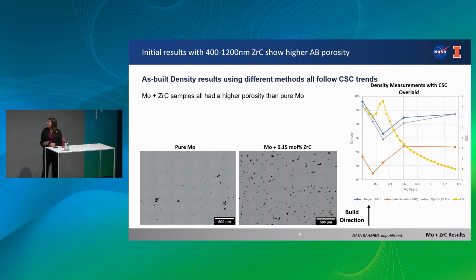If you take the densities, you can see that as the crack susceptibility is highest, our densities tend to be the lowest. Although we were not able to actually achieve a density that was as high as pure molybdenum, we have seen some promising results.